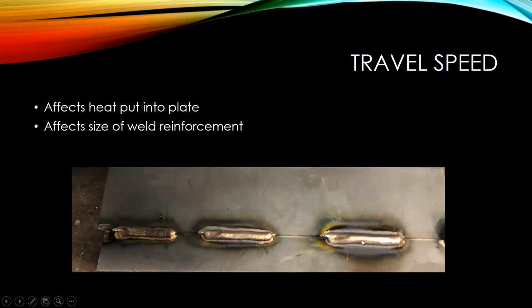So looking at these three welds, you can see a size difference between them. Here I was using a rather slow travel speed. The middle weld, I had picked up the pace a little bit as I was moving down. And then the third weld, I was really traveling fast as I was going across there. So just a couple of things to keep in mind. It'll affect the heat going into the plate. The slower you're traveling, the more heat you'll get. The faster you travel, the less heat you'll get into the plate, and then it also affects that weld size.